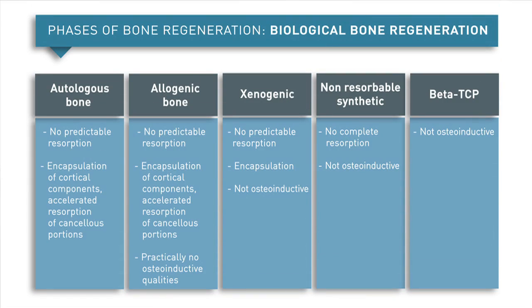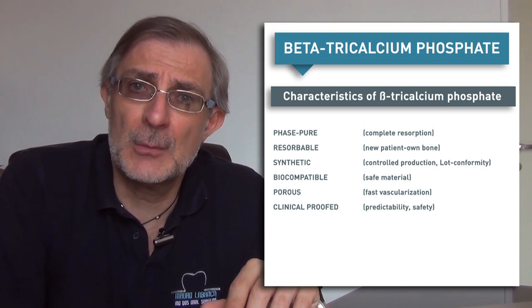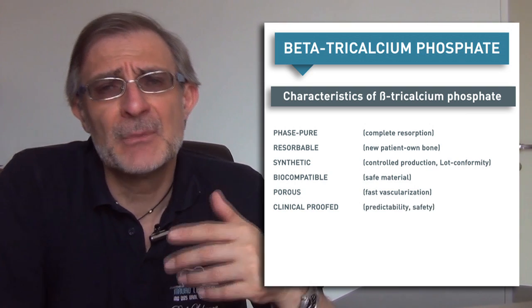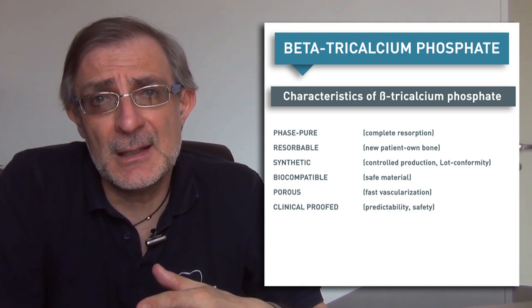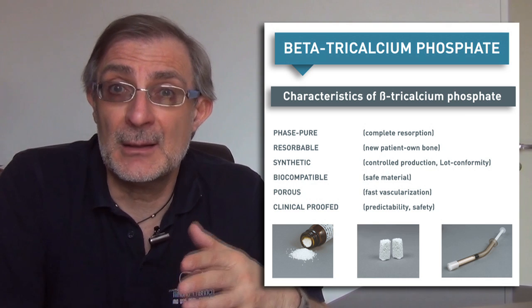Given that, I think that if we want to define not really the best in the world, but at least one of the better materials we can select for everyday use in our practice, beta-tricalcium phosphate can fulfill the expectations of normal dental use — not only for the oral surgeon, but also for the general dentist — because of the characteristics of this material: it is totally resorbable, safe because it is synthetic, and not expensive, and can be easily used for several applications in our dental practice.